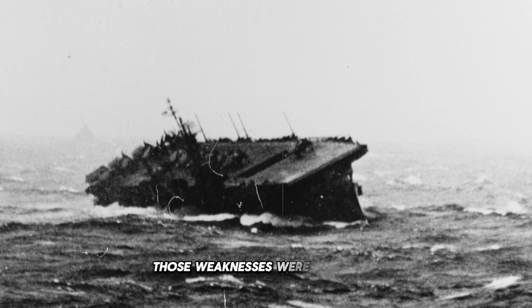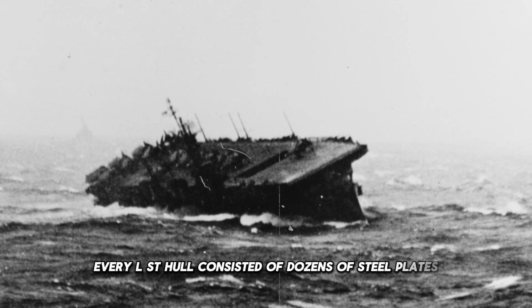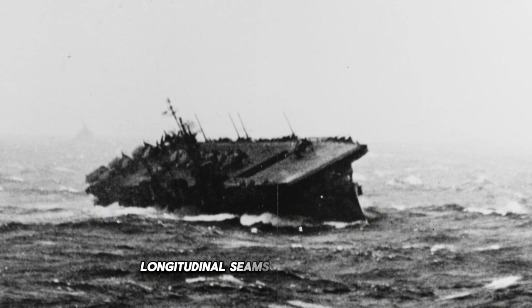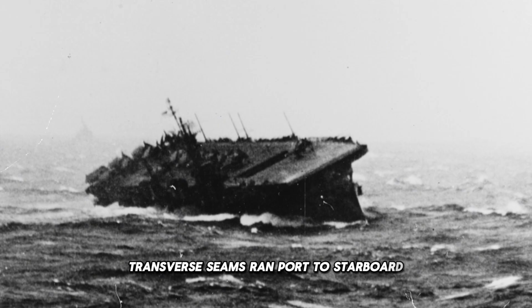Those weaknesses were the welds. Every LST hull consisted of dozens of steel plates welded together in a grid pattern. Longitudinal seams ran bow to stern. Transverse seams ran port to starboard. Wherever those seams intersected, wherever the tank deck met the outer hull, wherever bulkheads joined the bottom plating, there were welded joints that became fracture initiation points under mine blast stress.